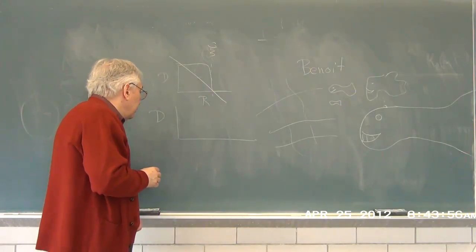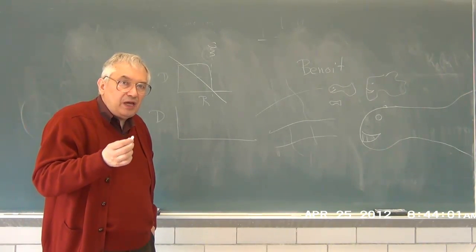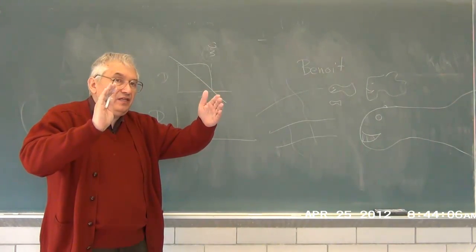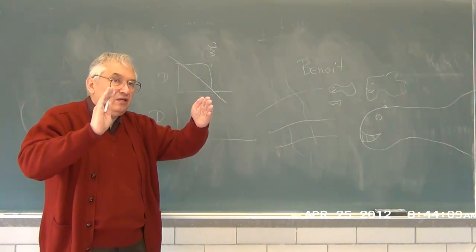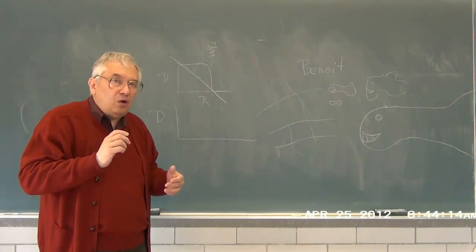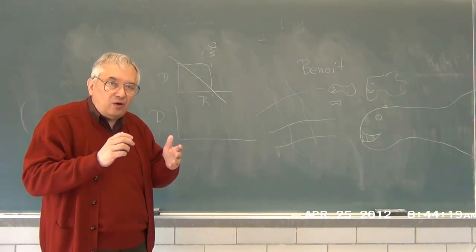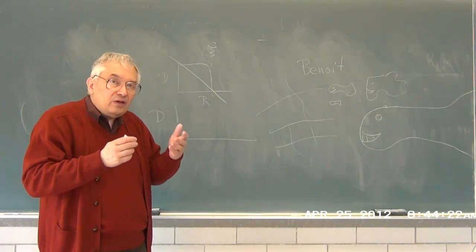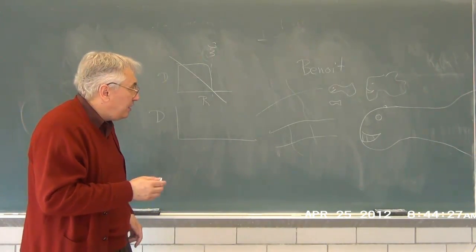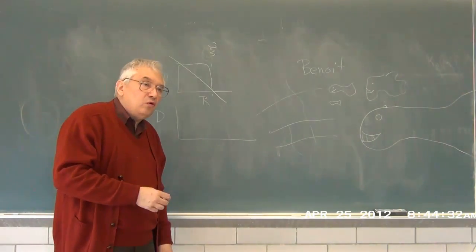And what Kirill discovered is that if you look at the probes, the light scattering spectra are bimodal. That means for motion on some fixed distance scale, there is some mode of motion which allows some of the particles to move quickly and others to move only slowly. And since you have these two relaxations, they each have a relaxation rate, and you can look at the behavior of the relaxation rate as a function of probe size.